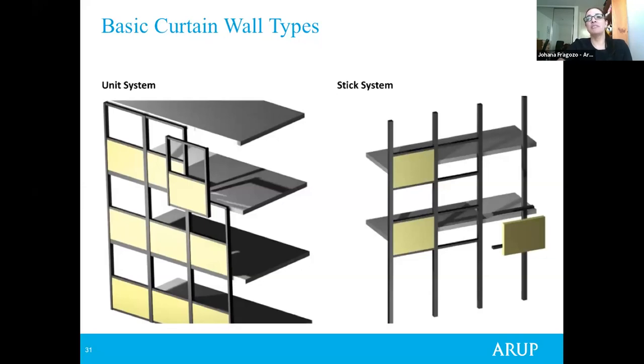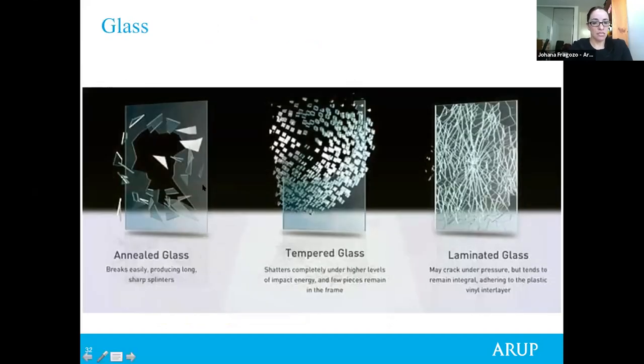And the difference between the different types of glass is the way that it breaks. Annealed glass breaks easily and produces long sharp splinters. Tempered glass shatters completely under higher levels of impact energy, and a few pieces remain in the frame. Laminated glass may crack under pressure, but it tends to remain integral, adhering to the plastic vinyl interlayer.